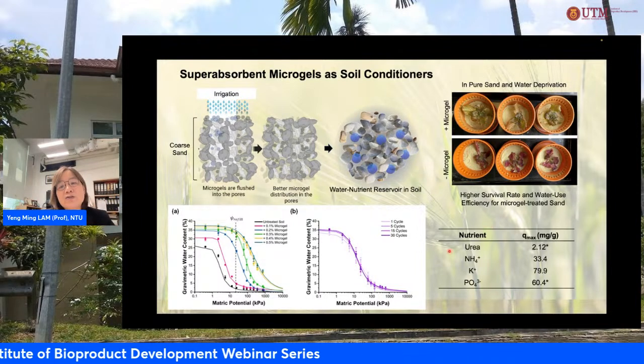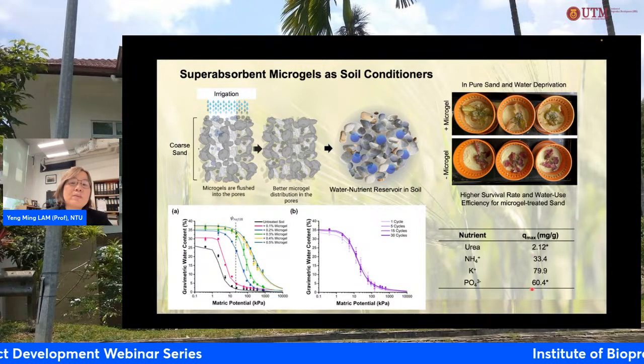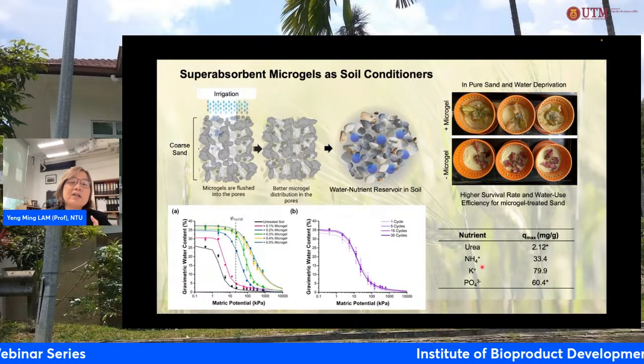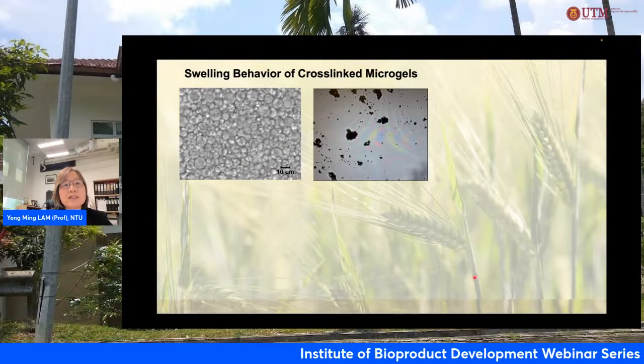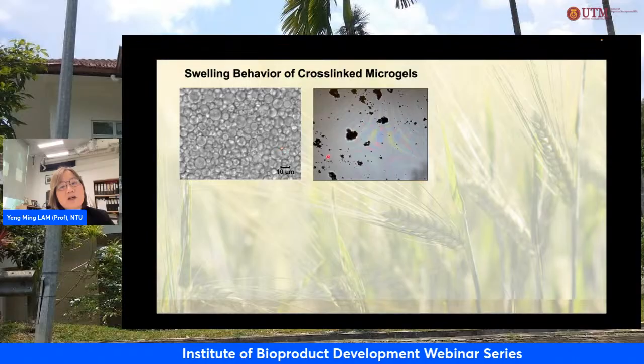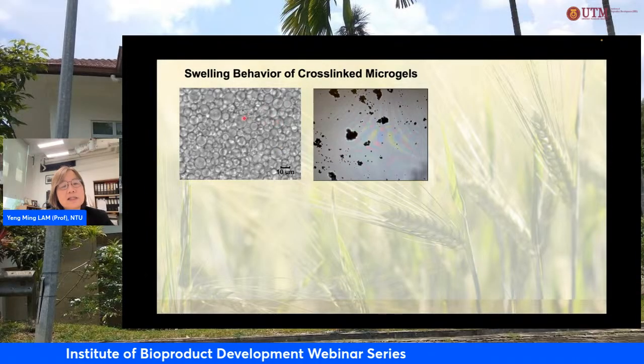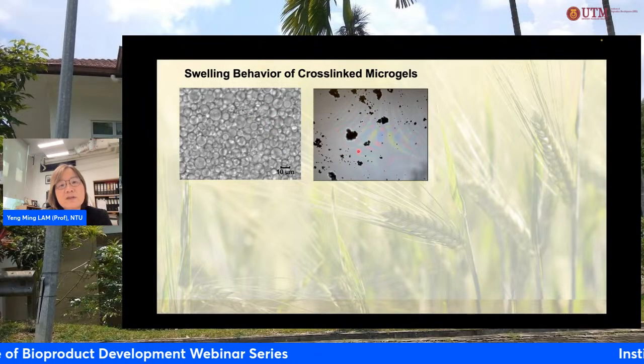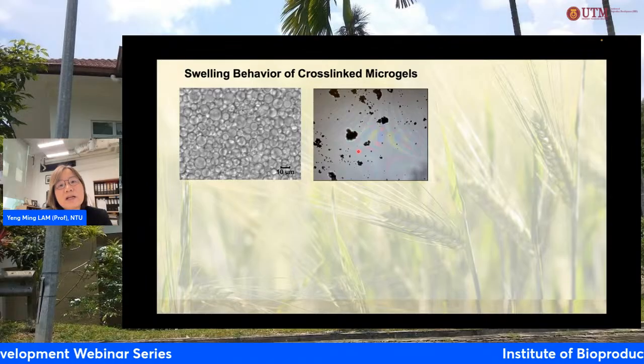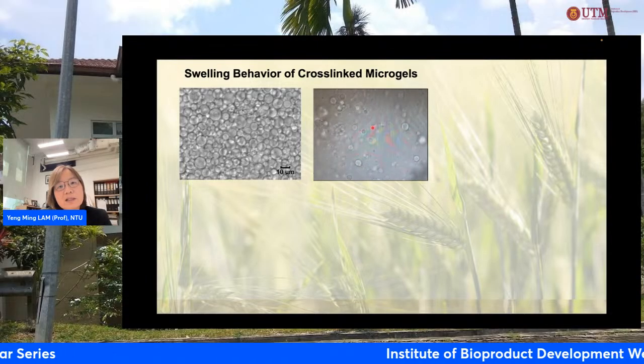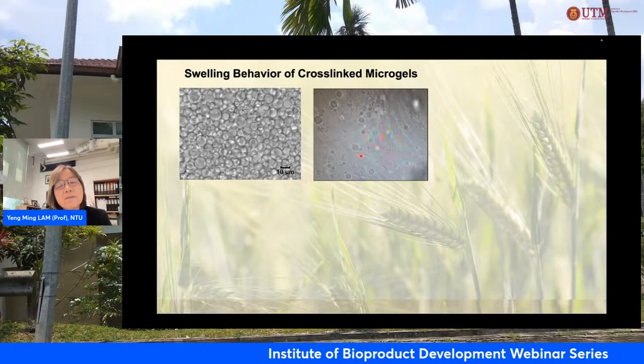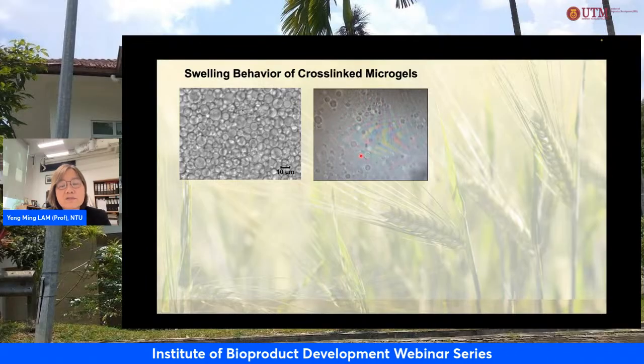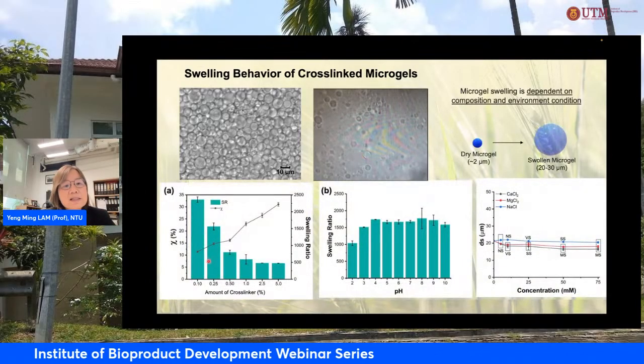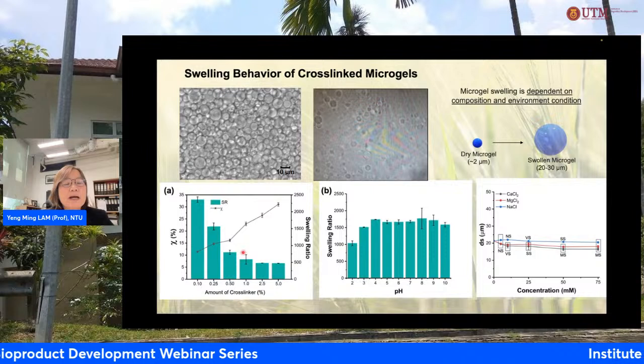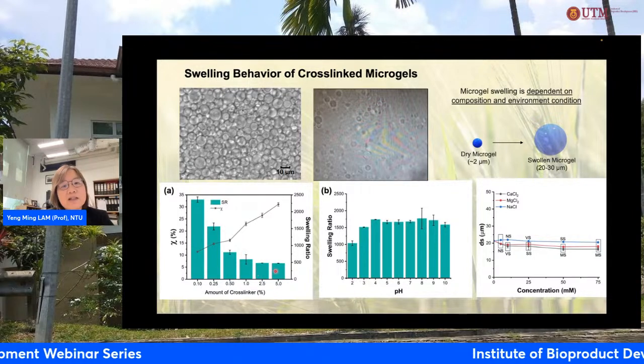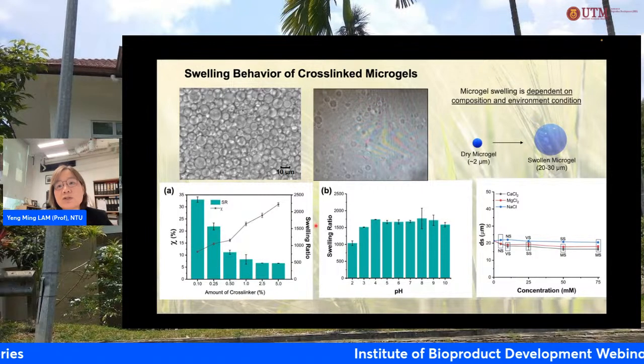So we can trap nutrients. The amount of nutrients that is trapped is actually very substantial depending on what you're looking at, NPK, any of these nutrients. And then if you look at the swelling behavior of this microgel, essentially these are already swollen gel. This is the video, which actually when we flush it with water, you see the gel swelling is very instantaneous, very fast. So essentially, this swelling ratio is actually controlled by the cross-linker that we have. So depending on the percentage of cross-linker, we can control this gel swelling.